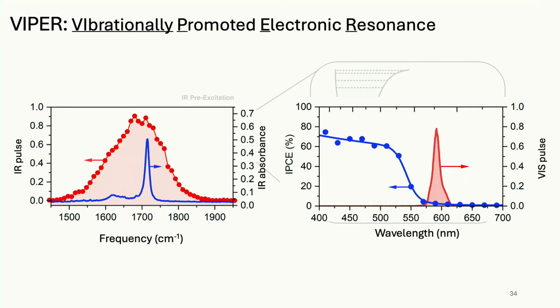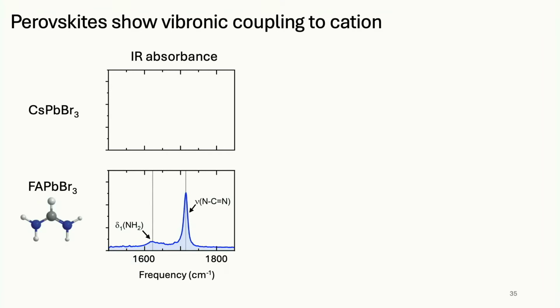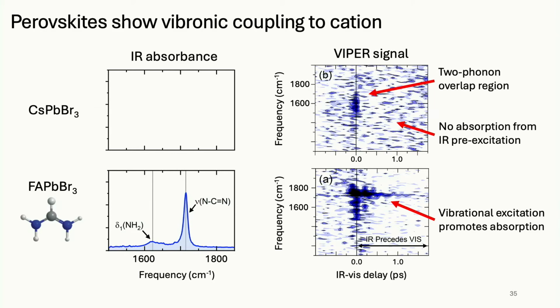So they use a broad pulse because it's going to be ultra fast, but the only thing it excites is this one mode on the molecule in the hybrid perovskite. Here, this is the molecule we happen to be using. It's called formamidinium, and the mode we're exciting is the carbon zigzagging back and forth between the two nitrogens. And here is their signal. If you don't do the IR pulse first, then you don't get a long-lived response in the VIPER signal. And if you have IR first, then only when you excite around 1700 do you get a long-lived vibrationally promoted excitation response.